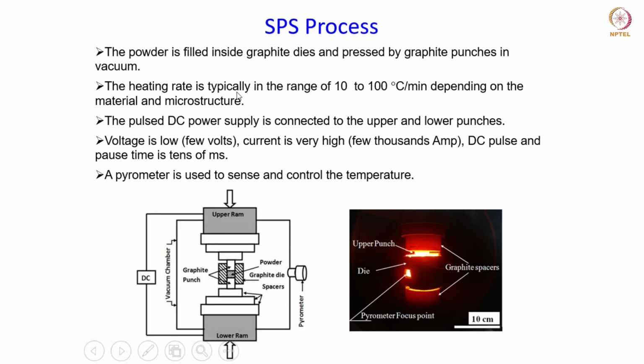The heating rate is typically in the range of 10 to 100 degrees Celsius per minute, but it can be higher also depending on the material and the microstructure which is desired. And as I said, a DC pulse is used as the power supply, and the DC power supply is connected to the upper and lower punches, and through these graphite punches the current is conducted to the powder which is in the die.